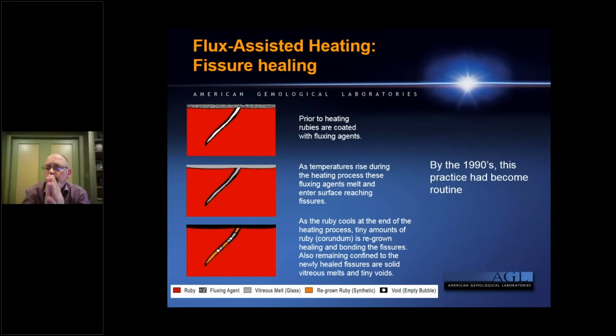And so what's taking place now along these previously open fissures is you have a combination of characteristics. You have thin seams of regrown corundum. In the strict sense, it's a synthetic. You have remnants of this undigested flux melt. It's a vitreous melt. It's in the strict sense a glass. And you have small contraction bubbles. And it's this combination of things which actually resides along these previously open fissures.